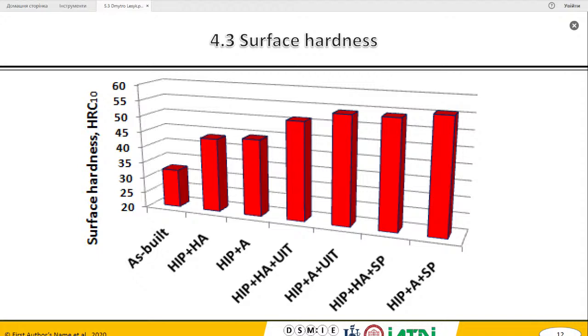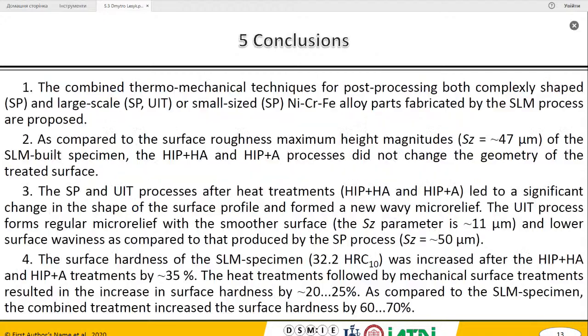The surface hardness of the SLM-built specimens is increased after application of novel post-processing techniques. In comparison with the heat-treated specimens, the surface hardness in the near surface was increased by 20% after the ultrasonic impact treatment, while the shot-treated specimens is slightly higher than that of the UIT processed specimens. Next, please.